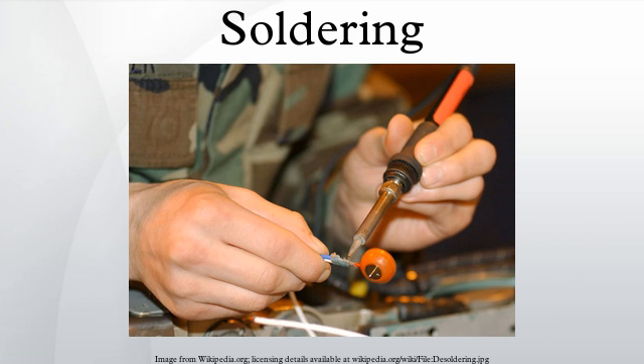If all metal surfaces are not properly fluxed and brought above the melting temperature of the solder in use, the result will be an unreliable cold solder joint. To simplify soldering, beginners are usually advised to apply the soldering iron and the solder separately to the joint, rather than the solder being applied direct to the iron. When sufficient solder is applied, the solder wire is removed. When the surfaces are adequately heated, the solder will flow around the joint. The iron is then removed from the joint. Since non-eutectic solder alloys have a small plastic range, the joint must not be moved until the solder has cooled down through both the liquidus and solidus temperatures.